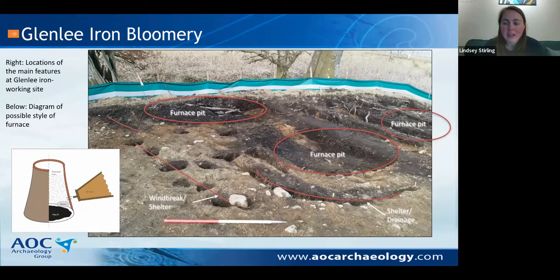So it's really exciting that the team were able to identify possibly 4 furnace bases at the site. I've not done a lot of background research into the site, but from what I gather, we often find spreads of metalworking material, but to actually find the locations of the furnaces is not so common. So this is quite exciting. It will be interesting to see whether all of these pits were in use at the same time, or whether we had the replacement of one another over a number of years.